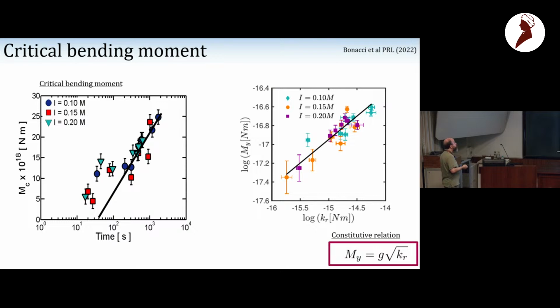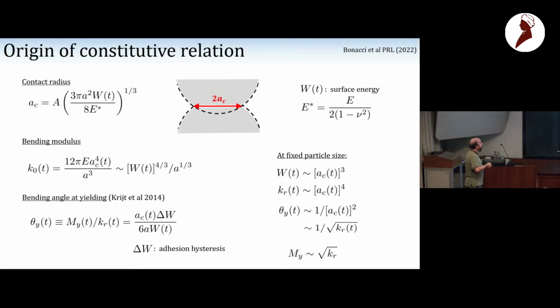And that's a detail, but we can go through contact theory, and there were some works by Kendall and others essentially dealing with this as a pinning problem. And if you deal with this as a pinning problem, you have an adhesion hysteresis, you have the surface energy which varies with time, and when you get that, you can basically back out the relation we get between the bending modulus and the rolling limit.